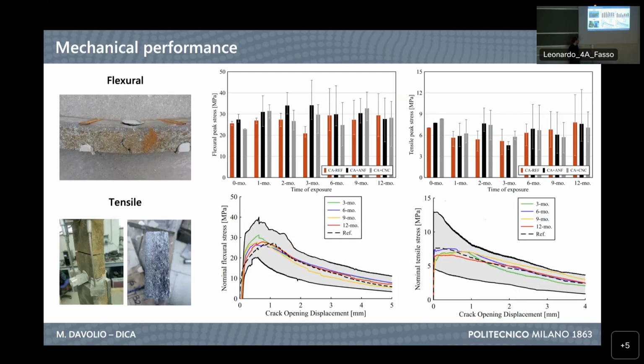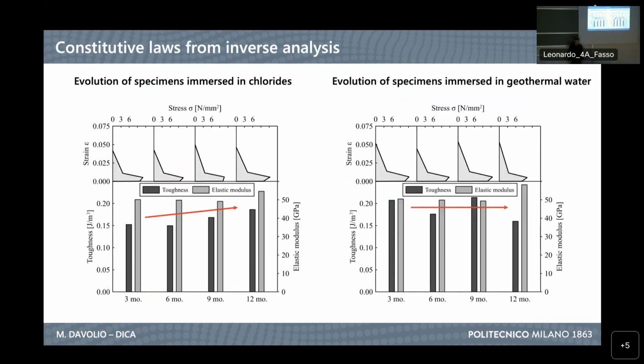And as you can see from the average curves, from the flexural test and from the tensile test, they are pretty similar, and they are all close to each other and inside of this envelope of the tests. And these are some pictures of the failure we observed. And we will further discuss tensile failure later.